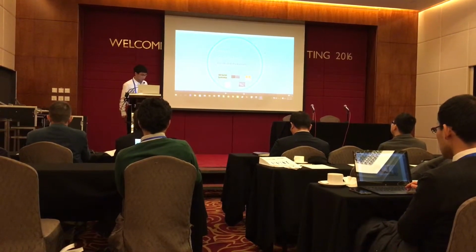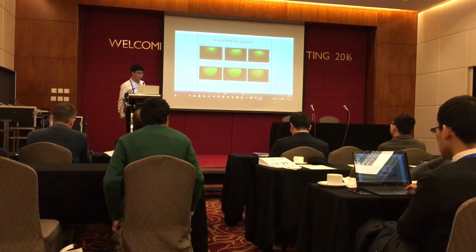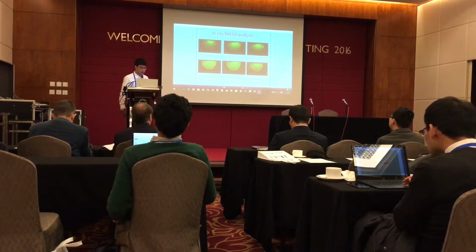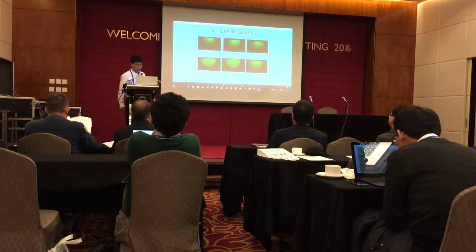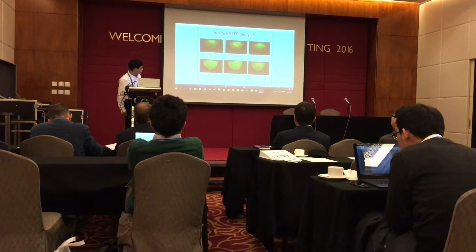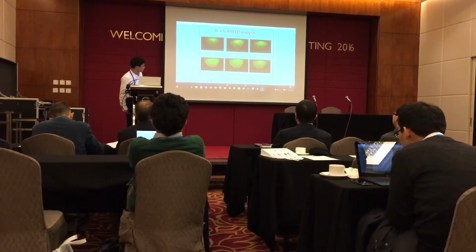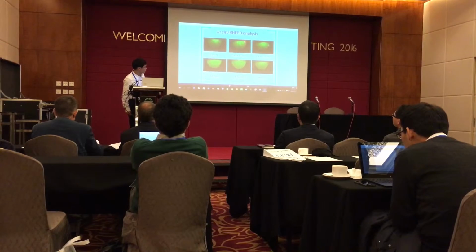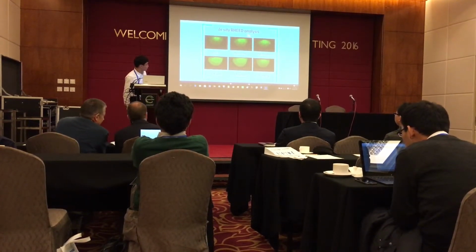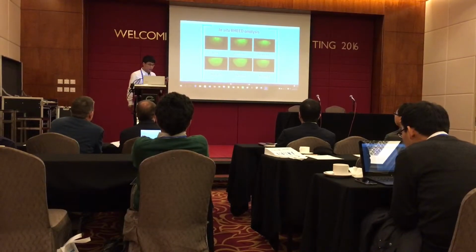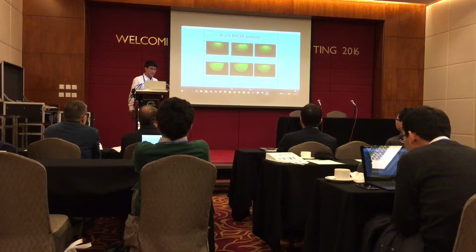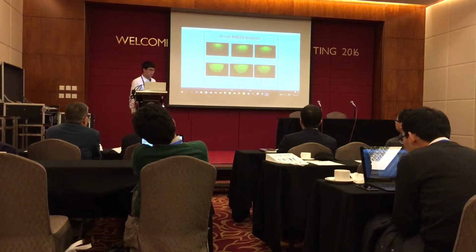Results and discussions. In situ RHEED analysis, RHEED is the acronym of reflection high energy electron diffraction. After thermal cleaning, the reconstructed silicon surface is streaky, you can see here. And after the pre-nitridation process, the RHEED pattern will turn foggy because a very thin amorphous silicon nitride film is deposited on the substrate.